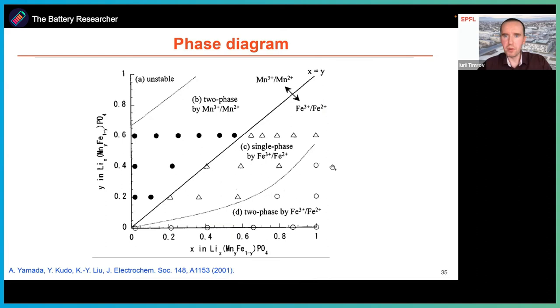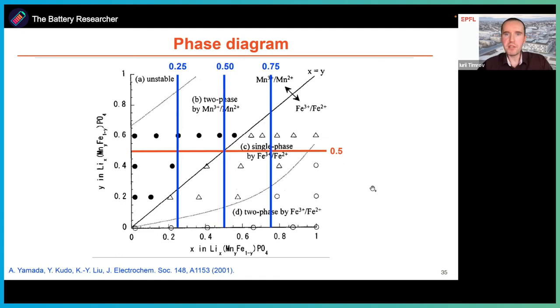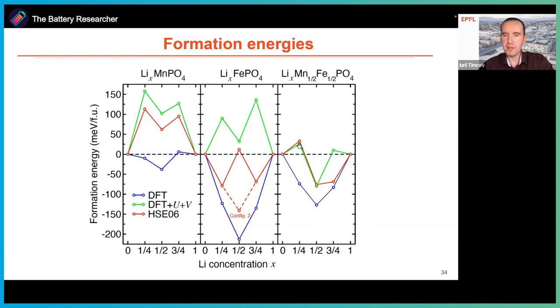So since we're considering the case of y equal to 0.5, we draw this red horizontal line, and we consider three concentrations, which are 0.25, 0.50, and 0.75. So we draw these three vertical lines. And we need to look at the crossings of these lines. So at the concentration of 0.25, we find that according to experiments, it is a two-phase process, which means that the formation energy must be positive. And in fact, in our calculations, we obtain positive formation energies, which is very good.